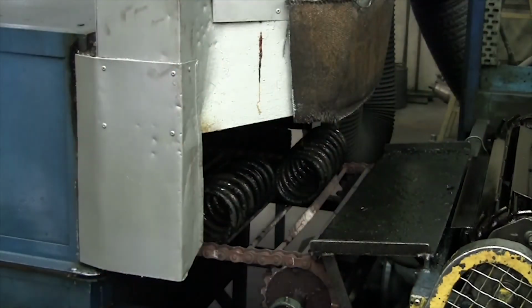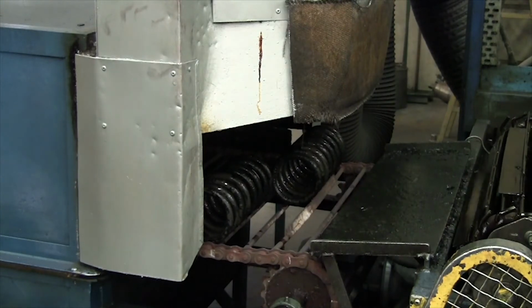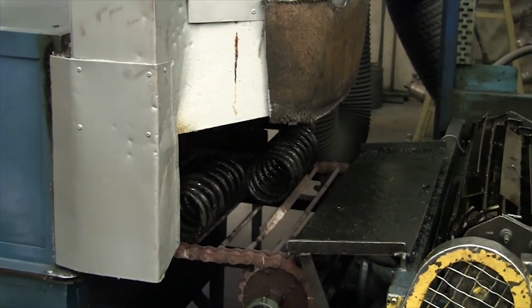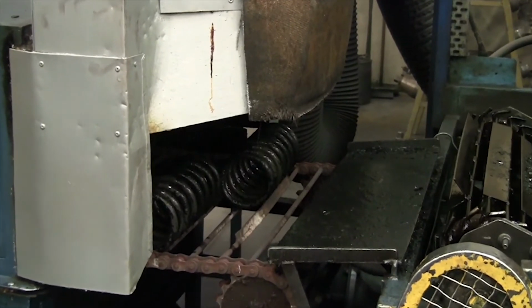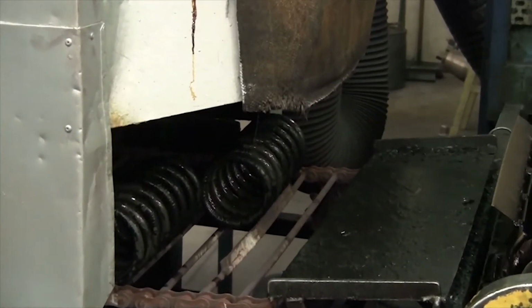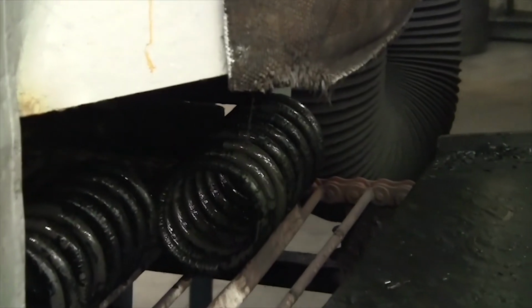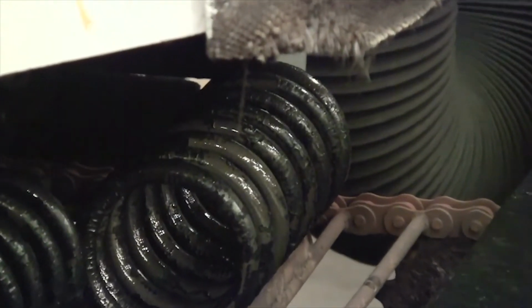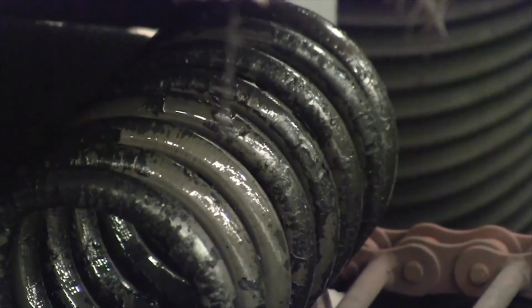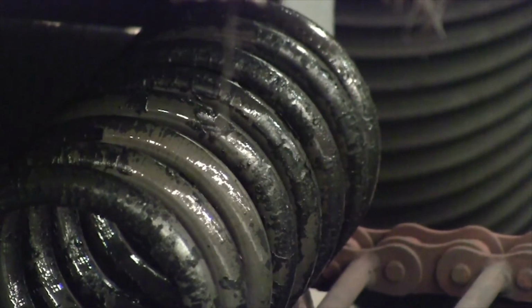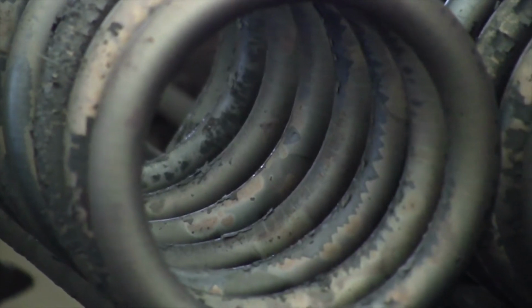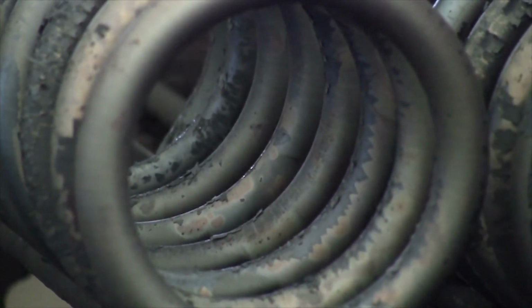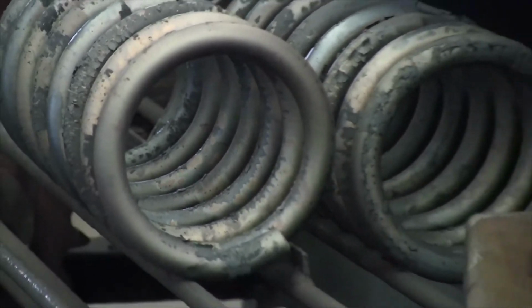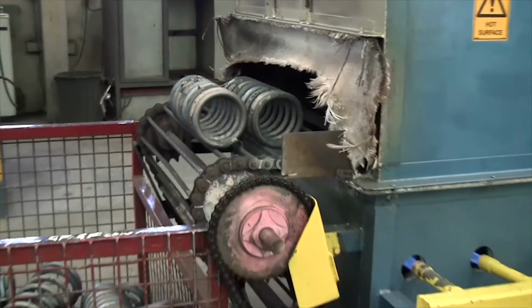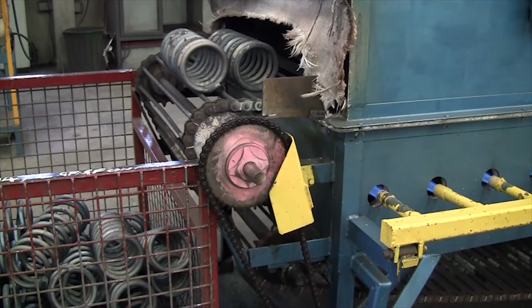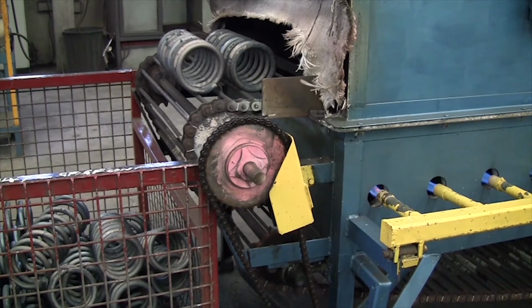From here, they pass through the gas-fired tempering furnace with an even temperature distribution that varies according to the spring wire diameter. This process ensures that the material maintains its elasticity. This segment of the procedure is very slow, as there is a need to heat the material uniformly from the exterior to the core, thus not creating any weak segments in the material. A good spring must return to its designed shape after a deflection. If a coil is not tempered correctly, there is a good chance that it will collapse.